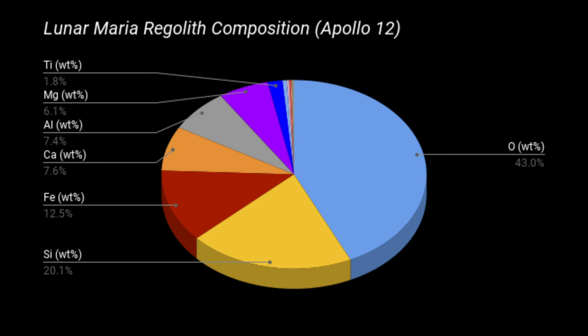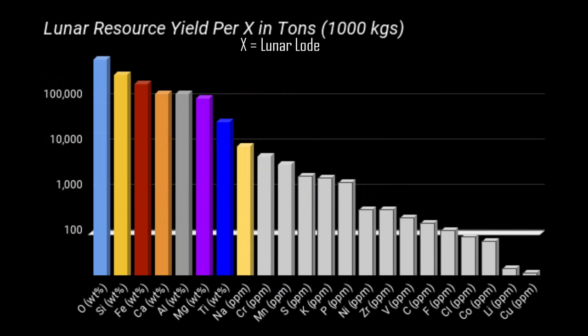Regolith in the Lunar Maria is about 36% metal, 12% iron, 7% aluminum, 6% magnesium, and 2% titanium, but it's mostly silicon and oxygen at 20 and 43% respectively, plus another half of a percent of half of the periodic table. Ideally, we want to use all of these elements. They're all useful, they're all equal.